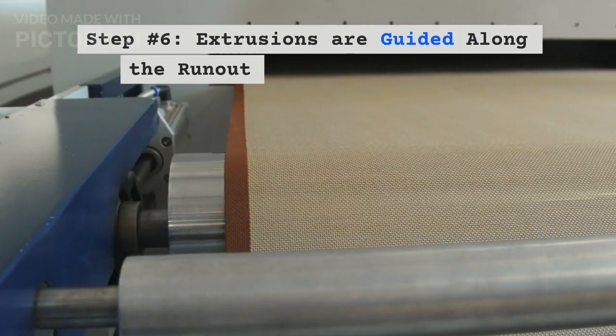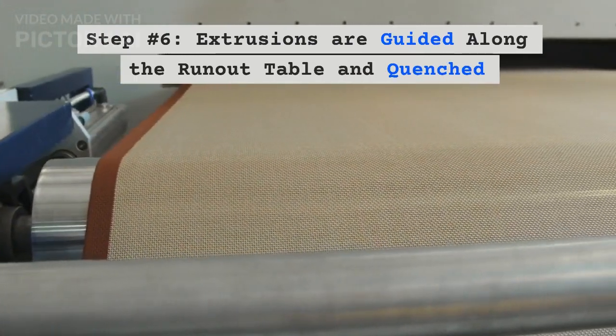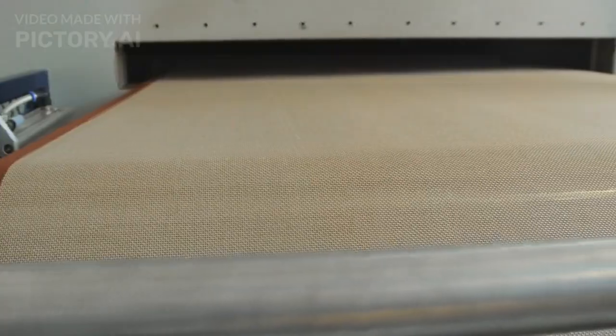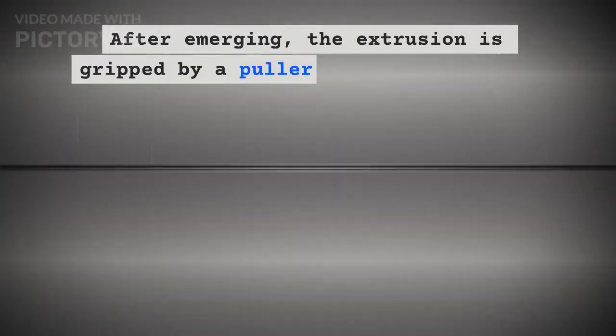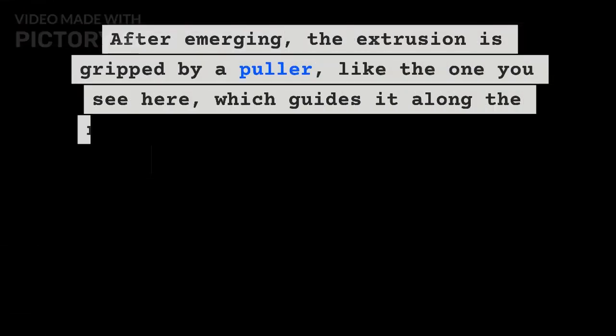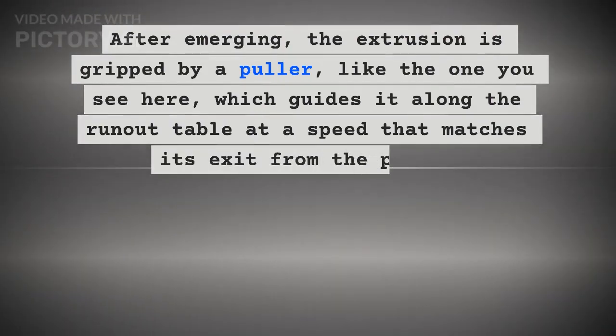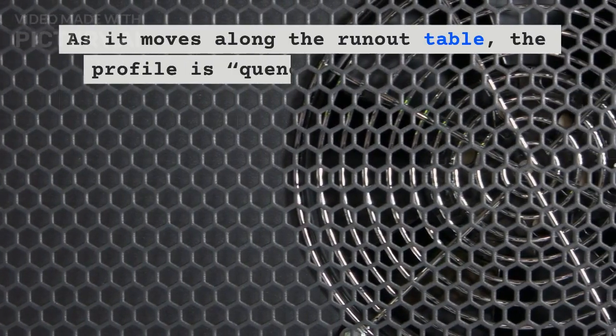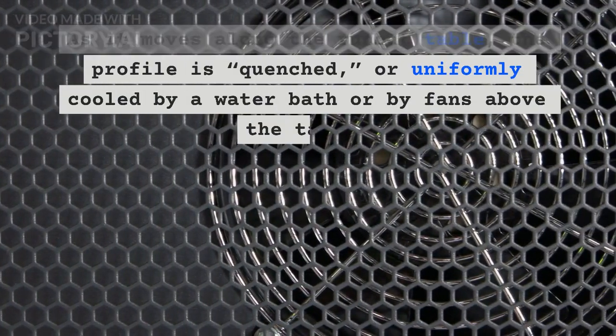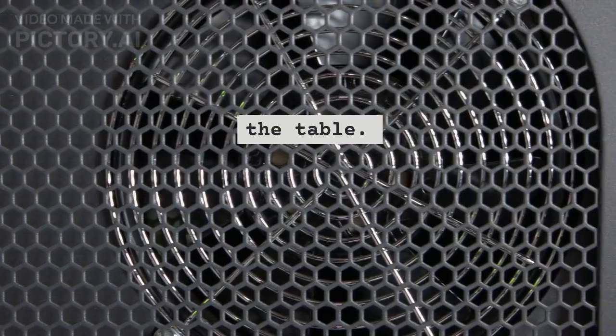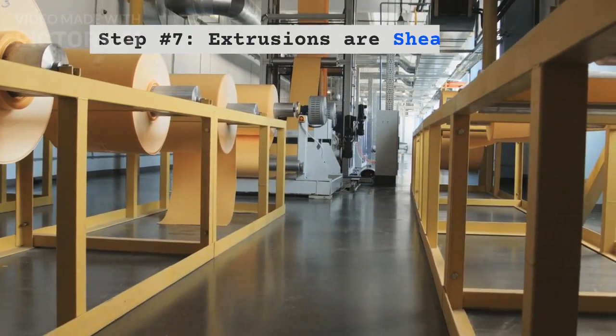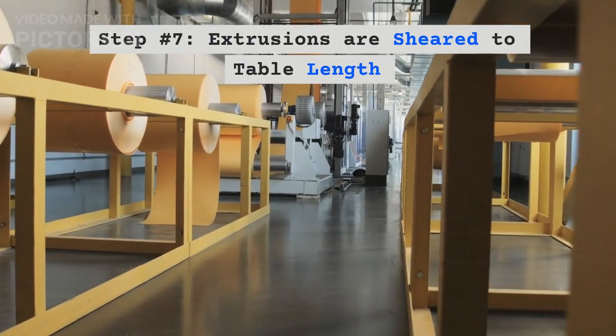Step 6. Extrusions are guided along the runout table and quenched. After emerging, the extrusion is gripped by a puller, like the one you see here, which guides it along the runout table at a speed that matches its exit from the press. As it moves along the runout table, the profile is quenched, or uniformly cooled, by a water bath or by fans above the table.